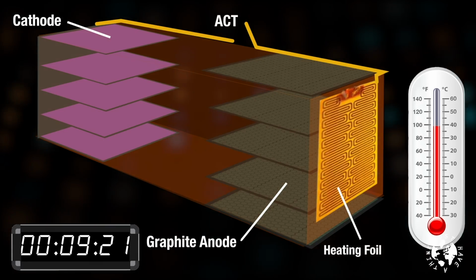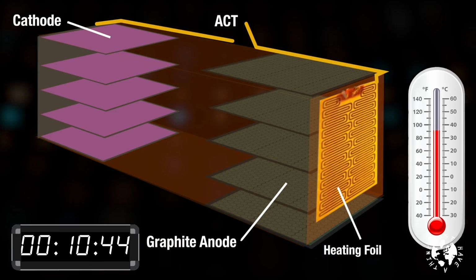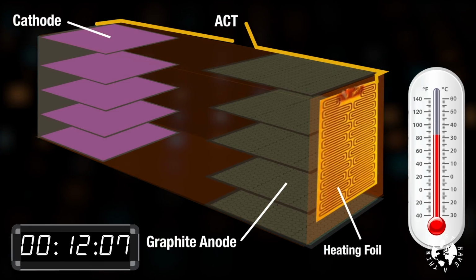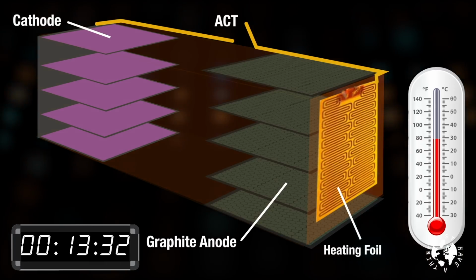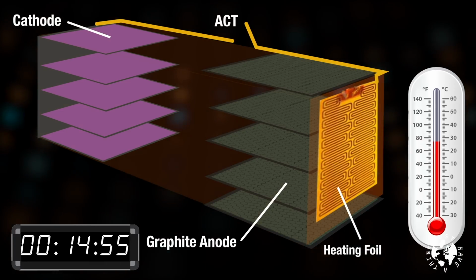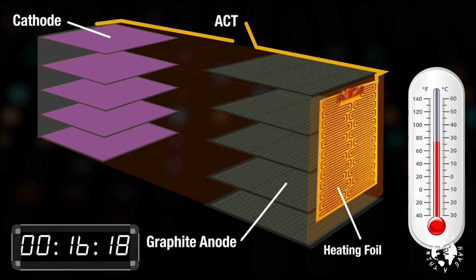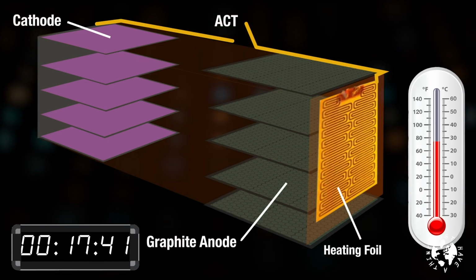During the discharge phase, the cell temperature dropped rapidly without the need for any external cooling. The average cell temperature during the charge phase was 49 degrees Celsius, and in the discharge phase, that dropped to 28 degrees Celsius. And it's that temperature difference that represents the asymmetry in the asymmetric temperature modulation method.